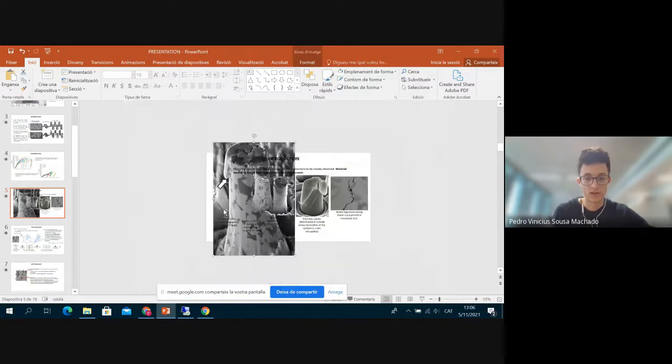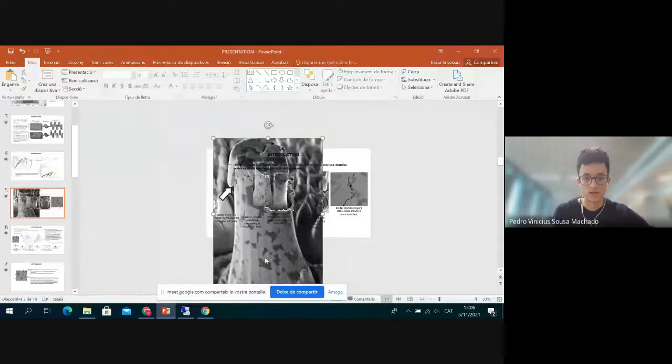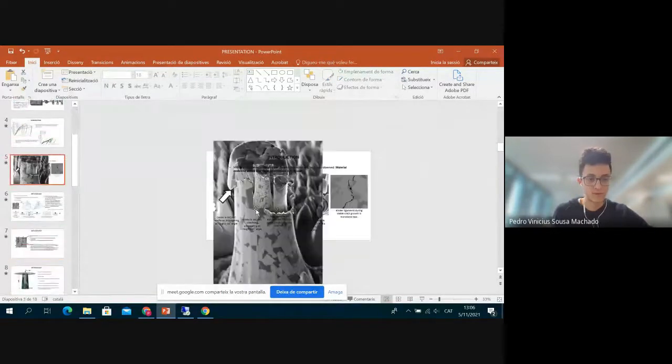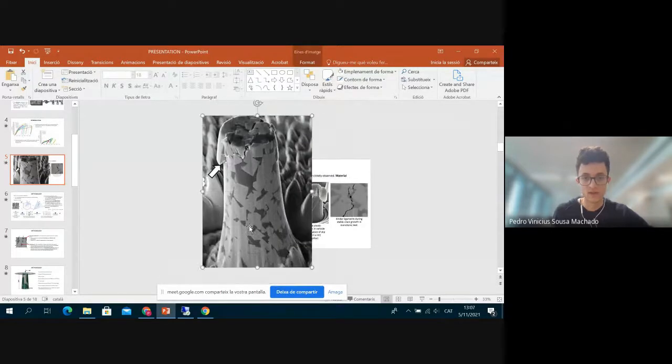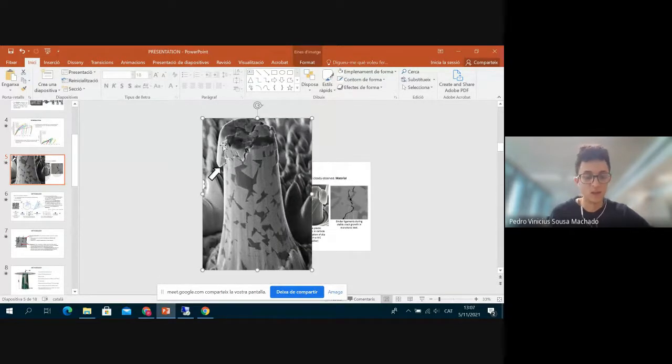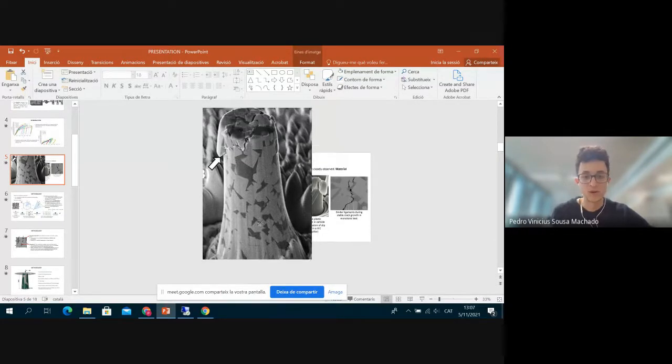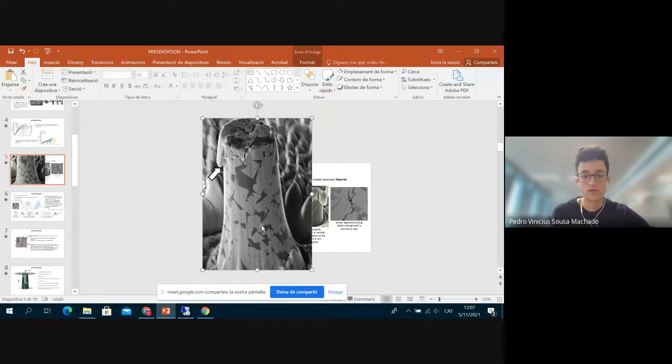So what's happening here is that the micropillar has this imperfect geometry, because when they make micropillars, these microscopic pillars, they always try to have them perfectly cylindrical. But of course, it's very hard at these scales. So they always have this small inclination, and here are imperfections caused by the FIB tomography.